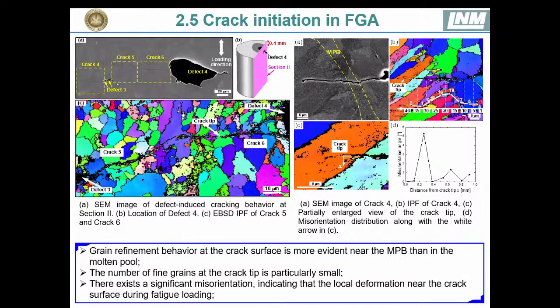And here in figure 1, we show 2 defects near the molten pool boundary. And we can see from figure B that a number of new fine grains appear between the crack surfaces. We can also see from figure 1 that crack 4 was observed and passed through the molten pool boundary. It also indicates that the grain refinement behavior at the crack surface is more evident near the molten pool boundary.